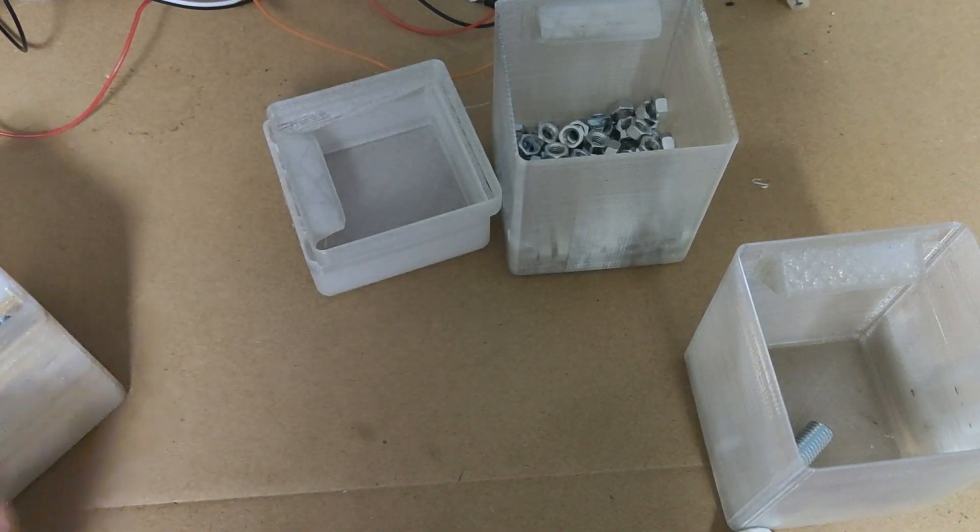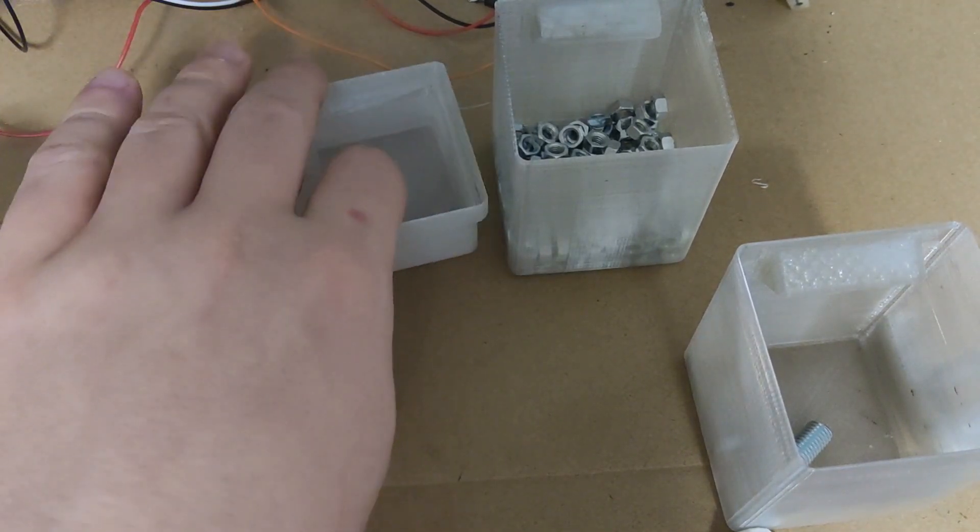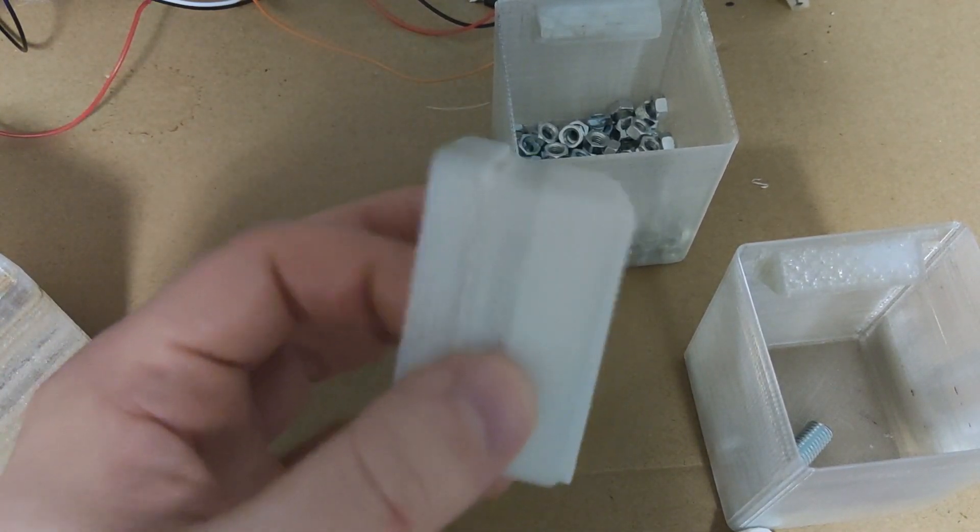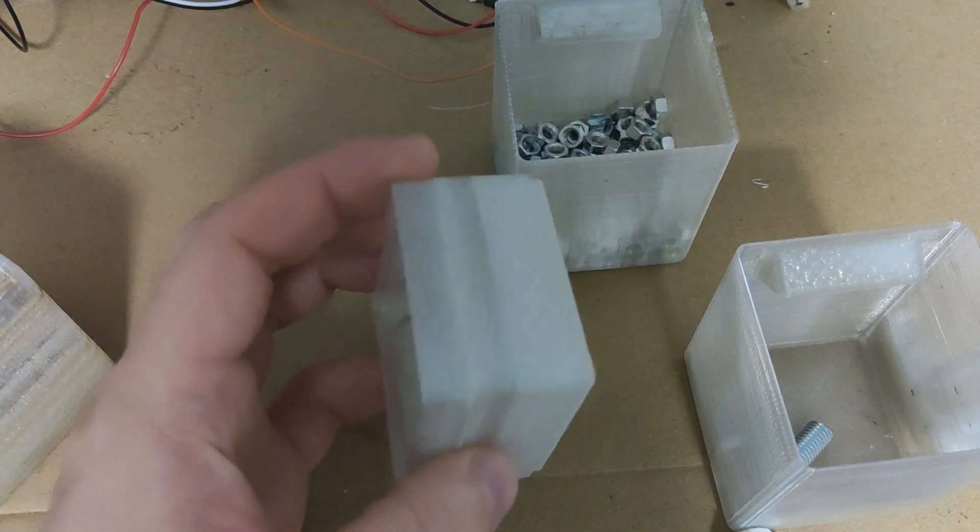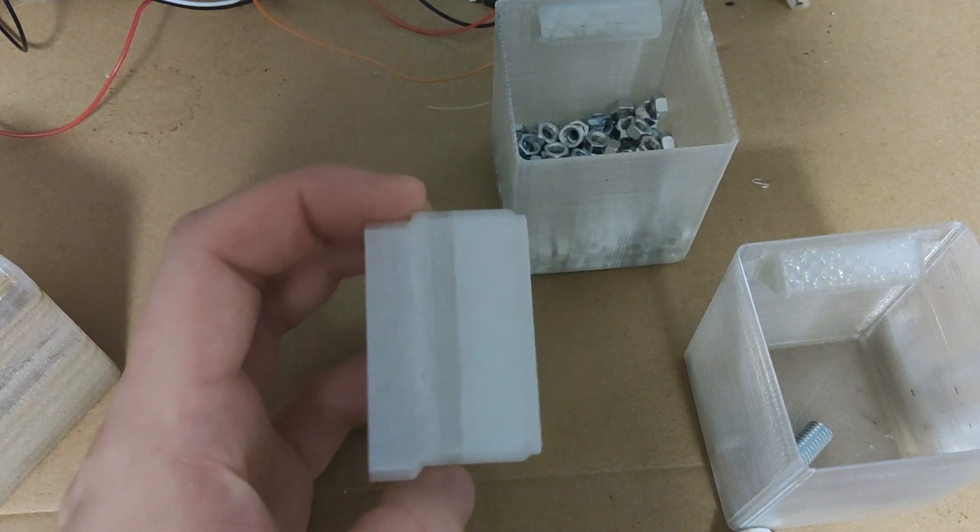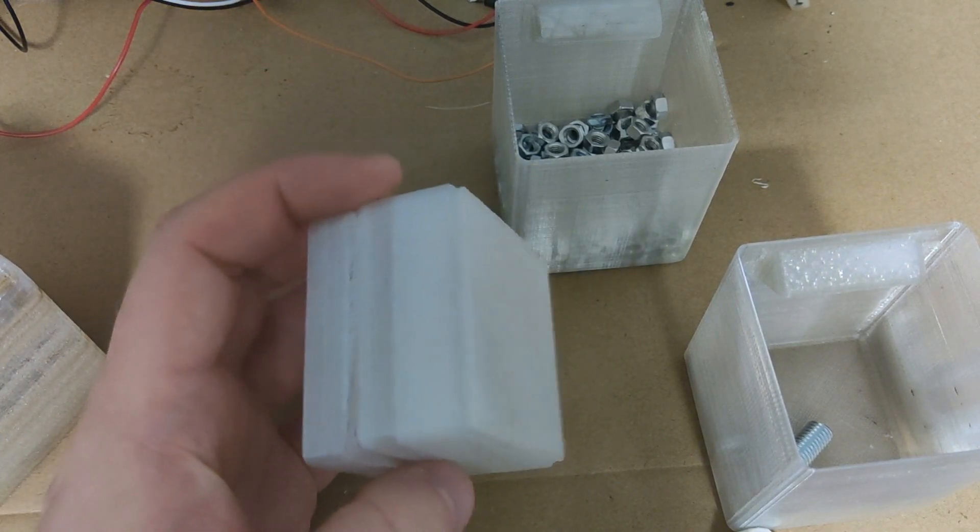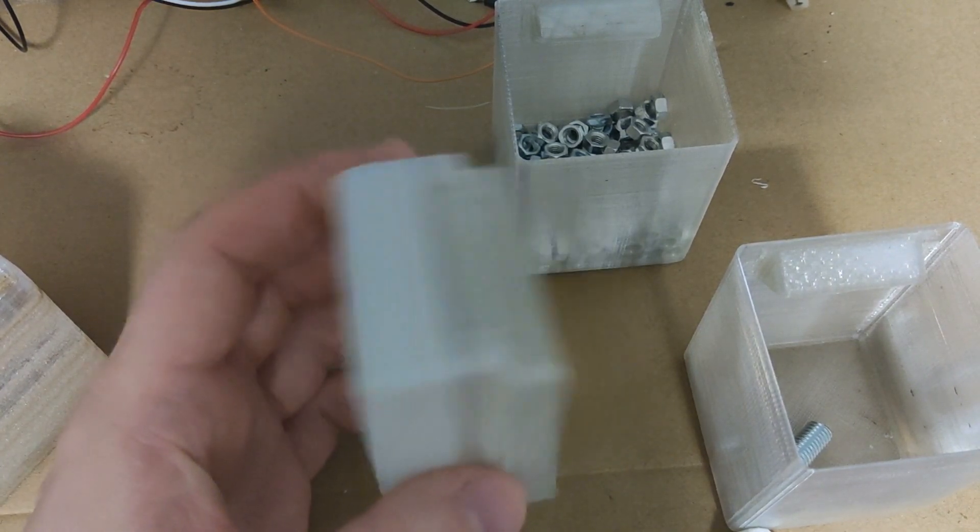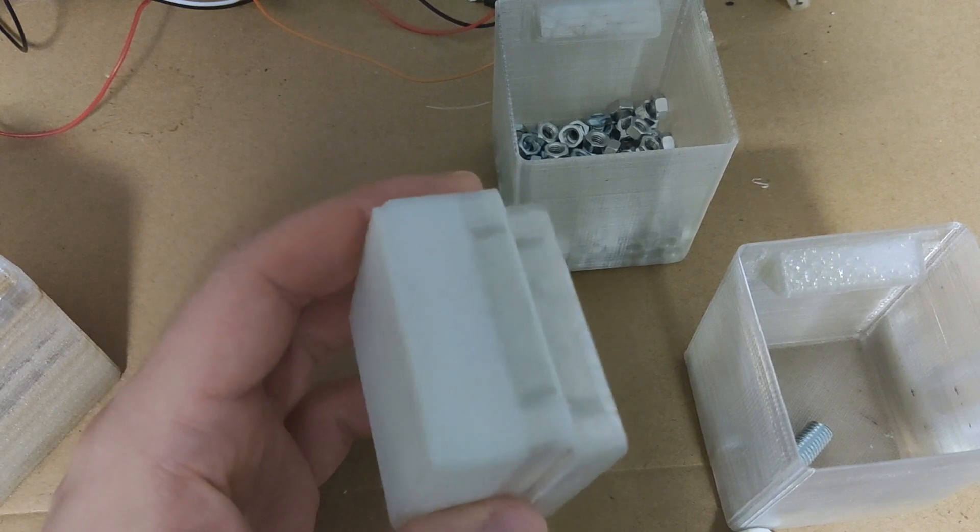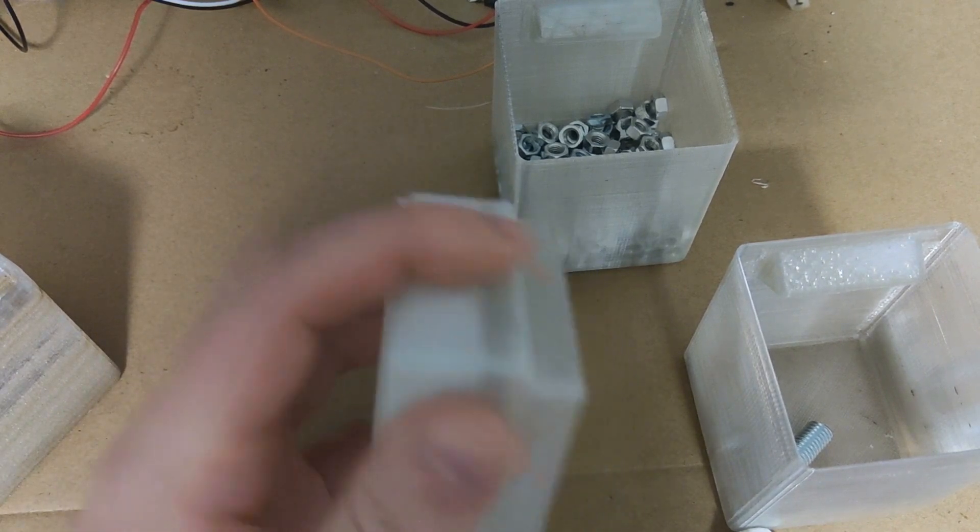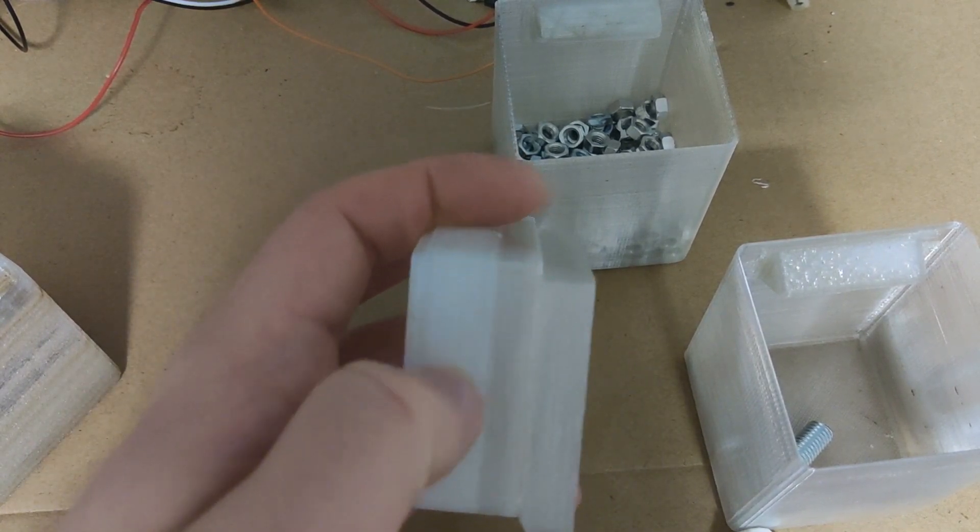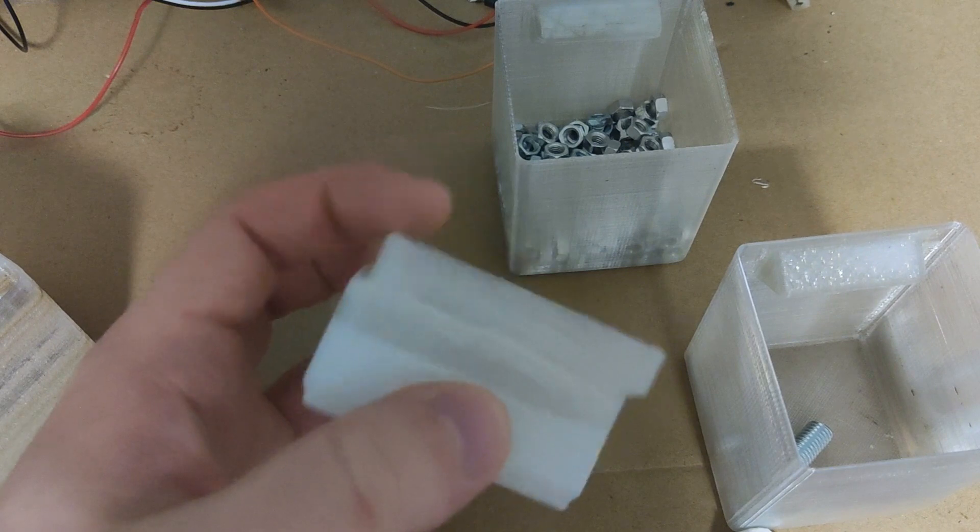Example number two is a box printed straight after pulling. Ultimately print failed because of my error, but as you can see surface is rough and bubbly, showing how hygroscopic this filament is.